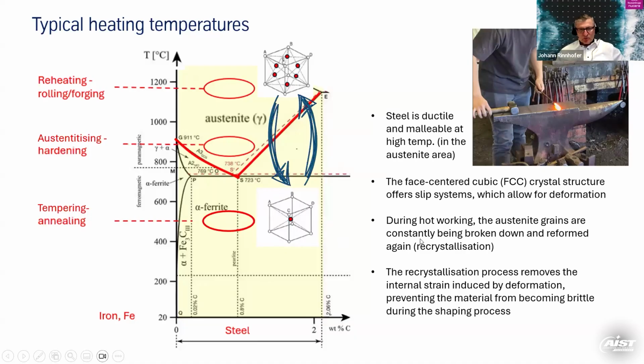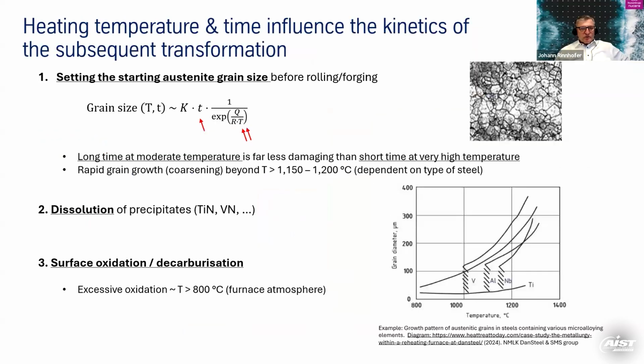And during a rolling or forming or forging process, the austenite grains are constantly broken down and also recrystallized again. So this is why we get a very specific crystal structure in a forged or rolled product. And we have all sorts of technologies like thermomechanical rolling and other things. We cannot go into too much detail here now. So apart from the temperature, we also have to set the starting austenite grain size before rolling, because that also will influence the final structure and final quality of the product in the end.